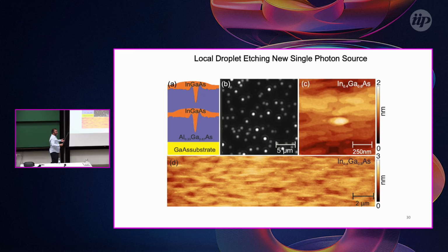And what was happening was the indium was diffusing inside the nano hole and forming Stranski-Krastanov indium arsenide quantum dots. You have basically two kinds of methods: indium arsenide Stranski-Krastanov inside the nano hole, and covered inside the nano hole. The optical quality for this kind of approach was not good. What I did was use aluminum gallium arsenide and deposit a material below the critical thickness of the indium arsenide Stranski-Krastanov formation. This way, I was able to really fill these nano holes with indium gallium arsenide, not with indium arsenide.